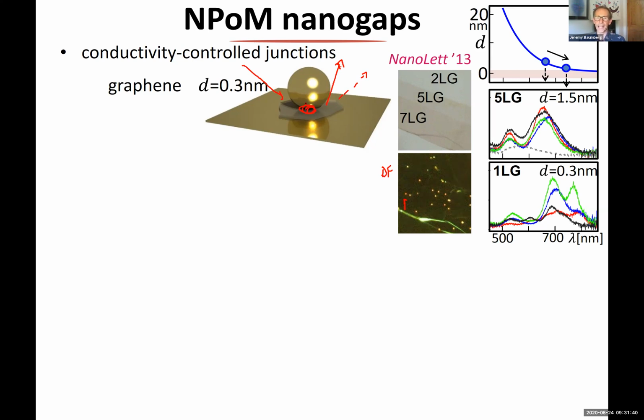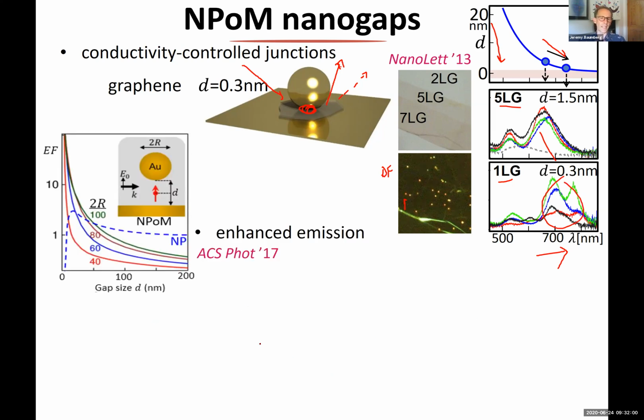So these colors tell you basically a lot of the features of the gap, and you can look as a function of the layers of graphene that you have in there. And indeed, you can see the mode redshifts as you go to thinner gaps here, then it will go to longer wavelengths. There's something else interesting going along here, a splitting, which we'll talk about later. So lots of things come out of this.